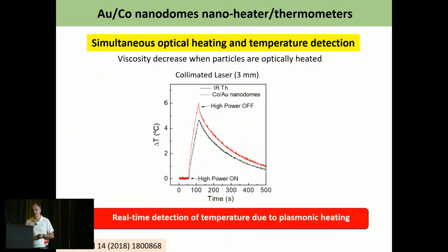And then, can we actually do the same using the laser? Can we warm up and measure at the same time using the nanoparticles? And here I show you the actual measurements. We put the laser on, and we measure with an infrared thermometer and using the phase lag of the nanoparticles. And indeed, both systems follow very nicely the same trend.